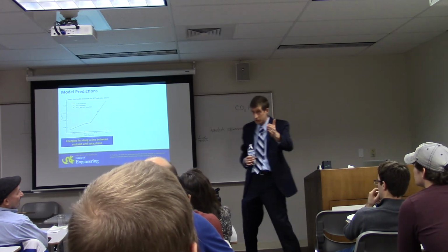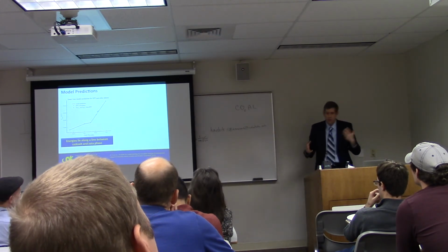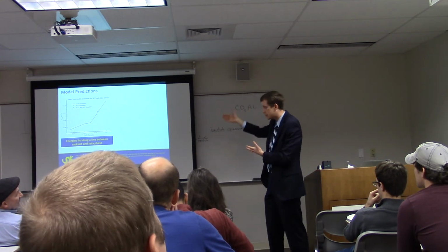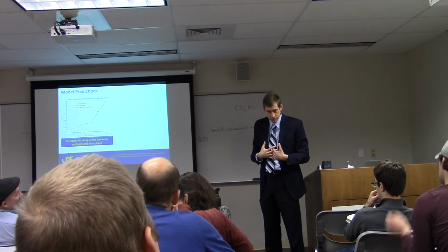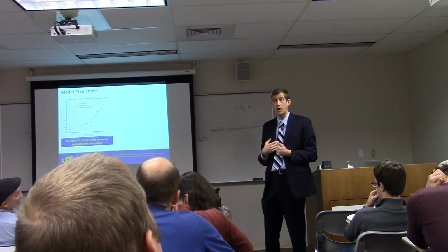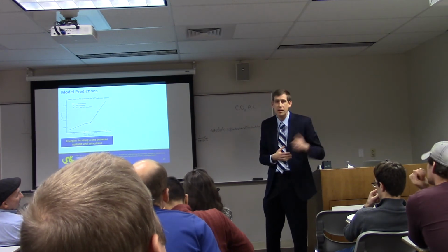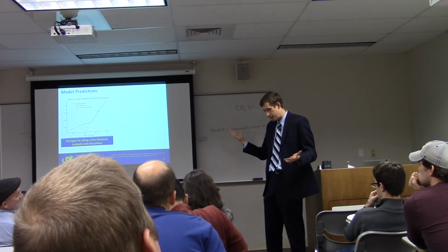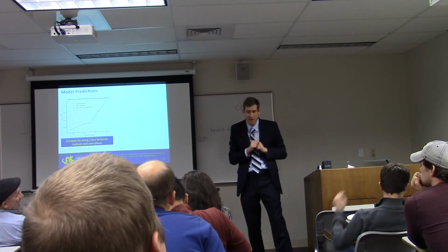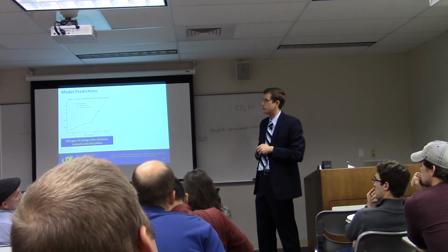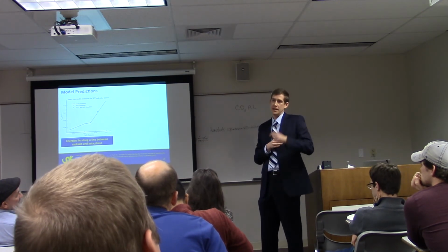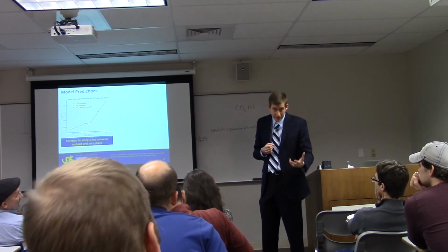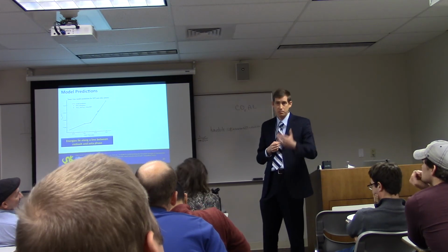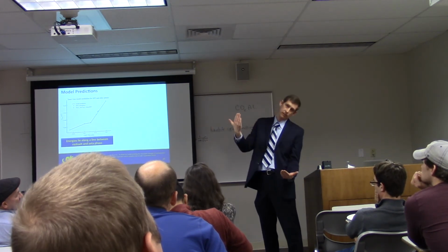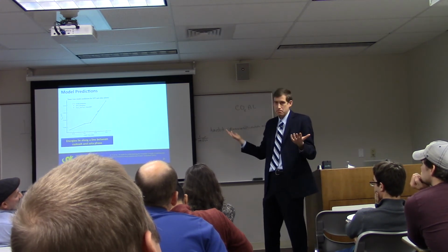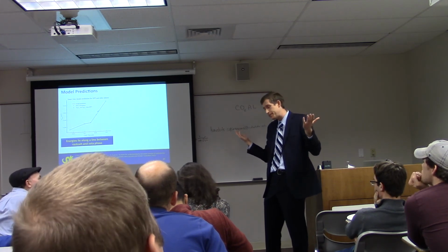In fact, to go back to the elastic constant question, I don't have this plotted, but one of the questions that we had was in terms of fracture toughness. Didn't have time to go into the many things that we've done. We said, well, we know that as you reduce elastic constants, materials tend to become more ductile. You get more metallic-like bonding, and you tend to get more plasticity, so your apparent fracture toughness is going to go up. So one of the things you can do is take DFT, simulate the elastic constants, and look at the trend. And the trend is almost exactly what you expect. No matter what exact phase I look at, as I deplete carbon, I'm breaking covalent bonds, I'm increasing the amount of metallic, and the elastic constants decrease. And you can look at the elastic constants from TaC to Ta2C, and the Ta4C3 sits right in between. There are no surprises. So I say, makes sense. You can't measure them experimentally, so that's the best we got.